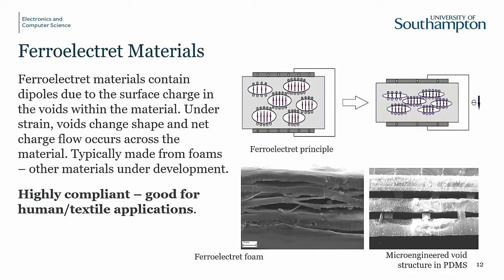So as I mentioned, these appear like a piezoelectric. If you squash them, you get electrical energy out. But inside the material is a series of voids. And once the material is charged, you get charge trapped across the surface of the voids, which form these electric field dipoles within the material. And if you squash it, you get a net dipole moment across the entire material, and you get a voltage signal and charge flow around the load circuit. These are commercially available in the form of these foams here. So this is a polypropylene foam here showing the voids. Or you can engineer the voids. This is using PDMS, something we did a few years ago. In both cases, they're very soft, very compliant, very stretchable, and they're ideal for human and wearable applications.